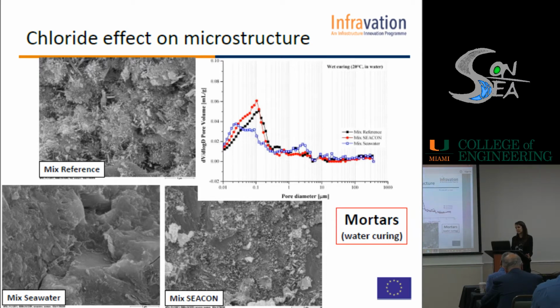So we decided also to perform MIP to understand the pore distribution, and in fact in the graph you can see that mixed seawater has a lower total porosity compared to the other two mixes, and this is in accordance with what we saw in the SEM images.